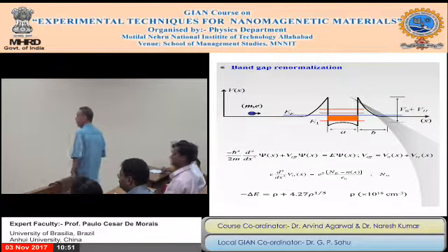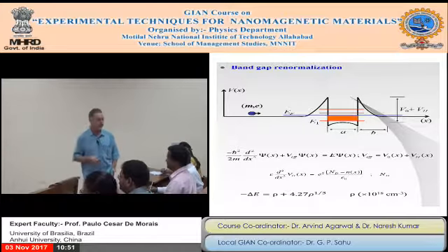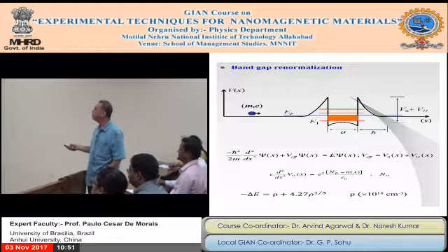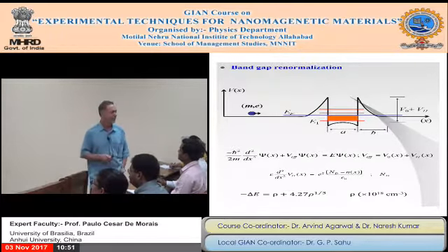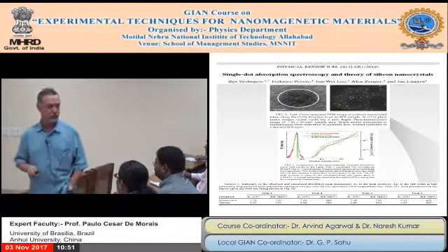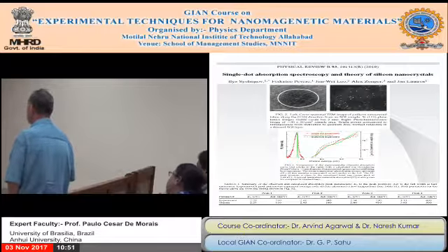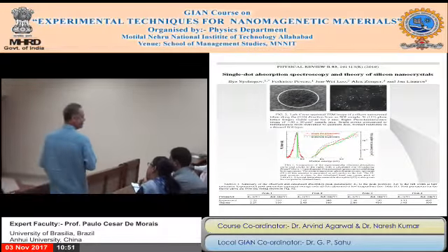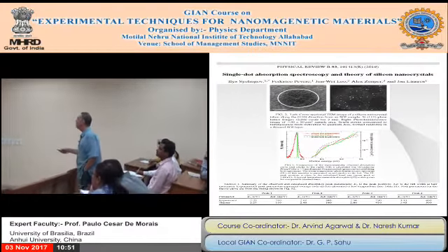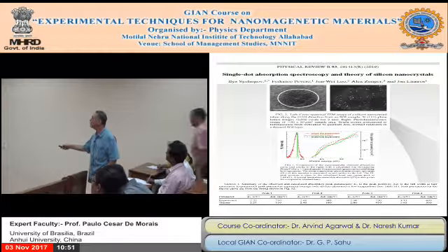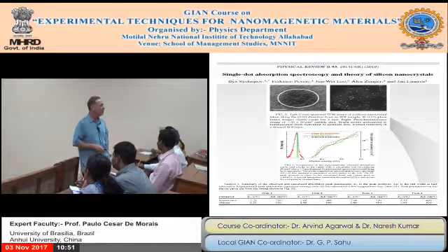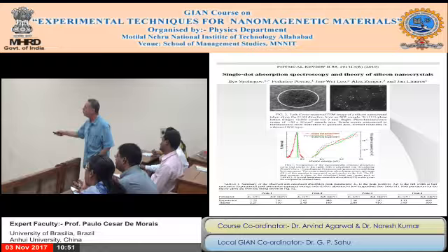Okay, now look at this paper, recent, last year. What they did, they fabricated small dots of silicon. Small. How small? 2 to 3 nanometers in diameter. And they were able to measure luminescence of each one one by one. And this is a picture of luminescence. Each spot like this, which looks like stars, is just one single dot.